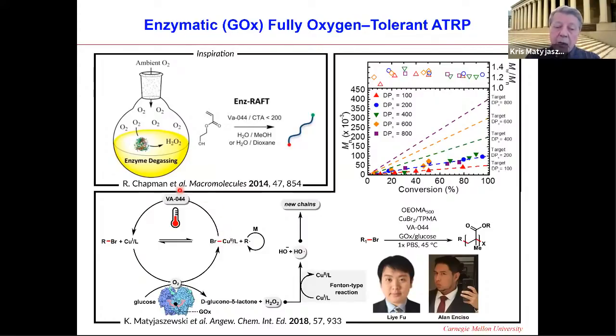We reduce copper 2 to copper 1 in the presence of a conventional radical initiator, low temperature, V-44. And then we use glucose and glucose oxidase and consume oxygen, forming gluconic acid or lactone and hydrogen peroxide. And hydrogen peroxide then unfortunately participated in this Fenton-like reaction, oxidizing copper 1 to copper 2 and forming hydroxy radicals, which produce new chains. So here polymerization worked very nicely, but you could see that the molar masses, instead of the predicted values, were significantly smaller. Instead of reaching, let's say, 400,000, they reach 50,000 only. So this is a problem.